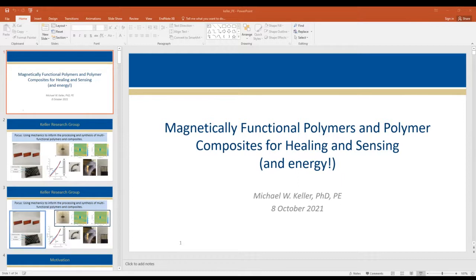So just a summary, we can demonstrate the ability to magnetically locate self-healing. It also demonstrated the ability of a vascular composite to actually mitigate damage via magnetic nanoparticle formation. And then a successful implementation of a multimodal damage detection approach. And then also we've been able to encapsulate an aqueous-based component and demonstrated the in-situ formation of magnetic nanoparticles. Both, I think, are firsts.